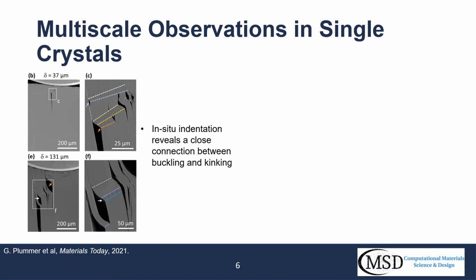So now let's move into some multiscale observations of kinking in MAX phases, which have only recently been enabled by new single crystal synthesis techniques. First, here are in situ SEM images of a MAX phase being indented, which show its high propensity for kinking. If we look at some of the more magnified images on the right, we see that in addition to the kink boundaries marked with dotted lines, some of the layers appear to just be elastically buckled with that continuous curvature. This indicates that there is indeed a very close connection between elastic buckling and kinking, as classical kinking theory would suggest.